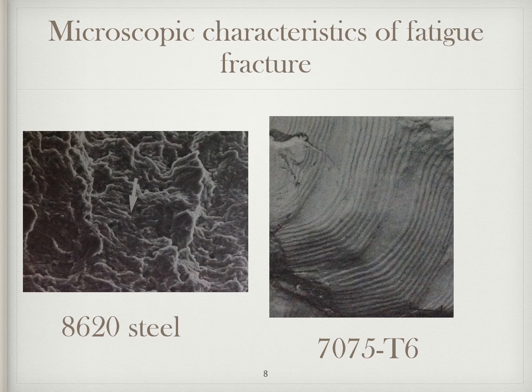The figure on the right side shows fatigue striations formed as a result of spectrum loading in a laboratory test of aluminium alloy 7075-T6. In this test, the specimen was loaded 10 cycles at a high stress, then 10 at lower stress, and alternated with these stresses as the fatigue crack continued to propagate. This produced 10 large striations, then 10 small striations alternately across the fractured surface. So here again we see the 10 large striations followed by 10 small striations, again 10 large striations likewise.